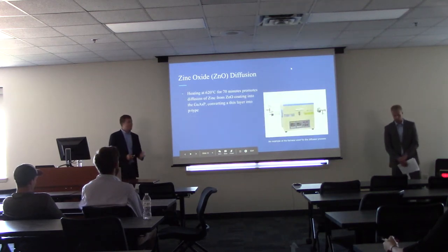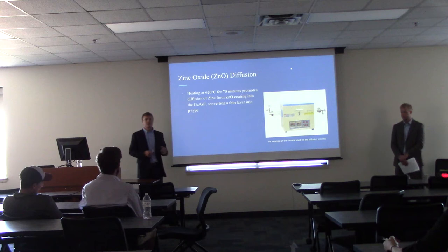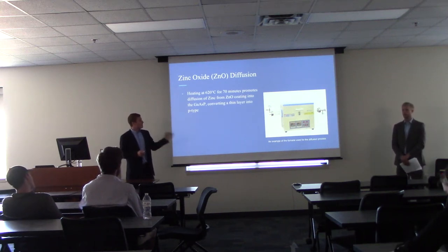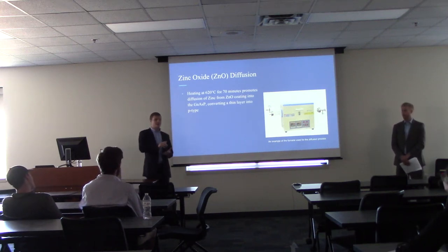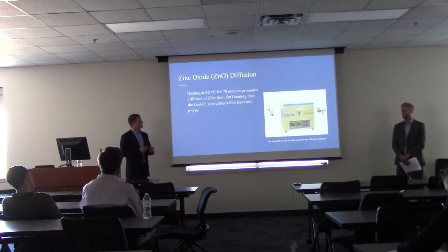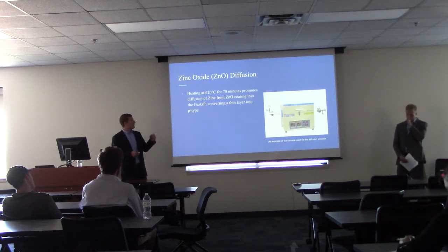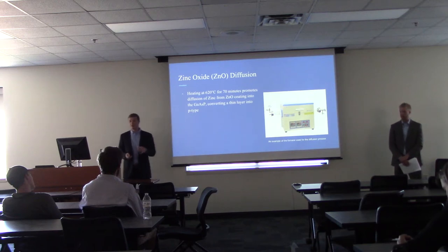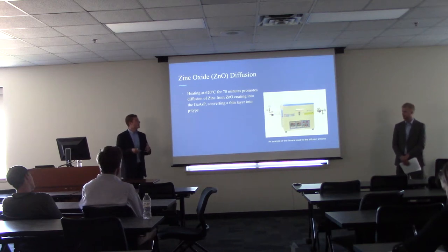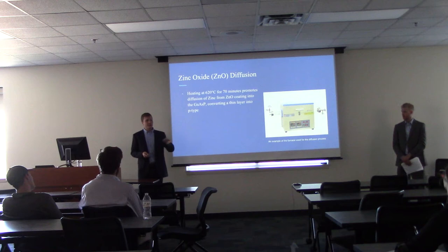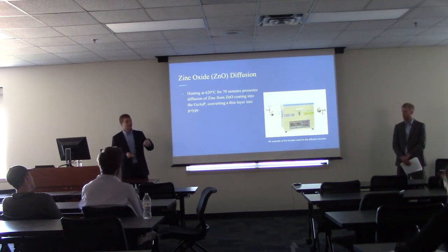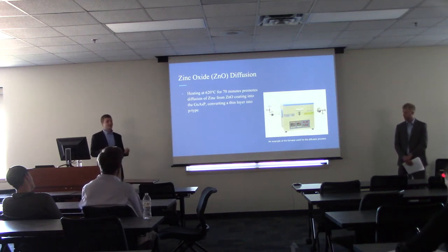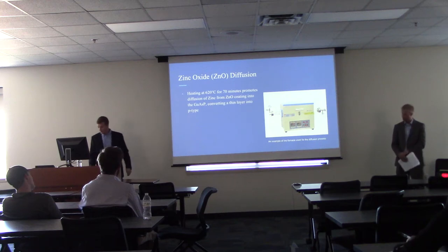The next step is the diffusion process, which actually creates the P-N junction. You take the sample after zinc oxide is deposited on the surface, place it in a furnace at about 620°C, and bake it for about 70 minutes. This converts a thin layer of the top of the gallium arsenide phosphide into a P-type layer, creating the P-N junction needed for our solar cell.